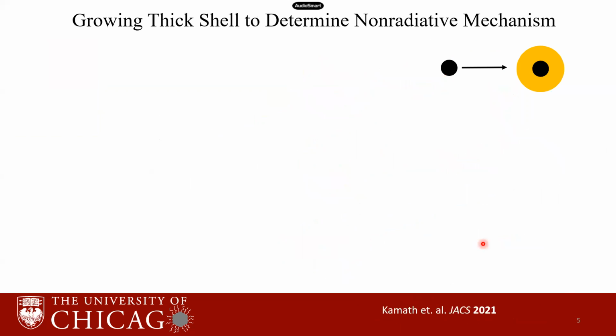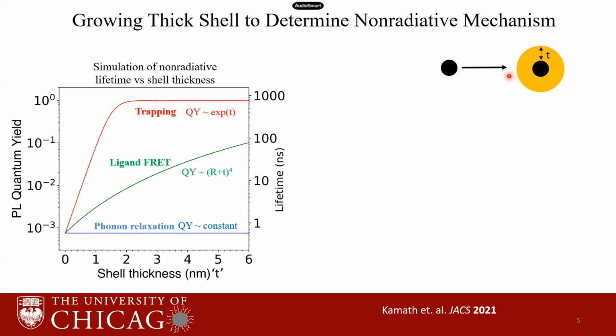So to find the mechanism of relaxation, I have designed a strategy to grow a thick shell around the nanoparticle. By growing this shell, we are separating the active core material from the surface of the nanoparticle. Since the three models obeyed fundamentally different physics, the growth of this shell has different effects on the non-radiative rate of these three mechanisms.